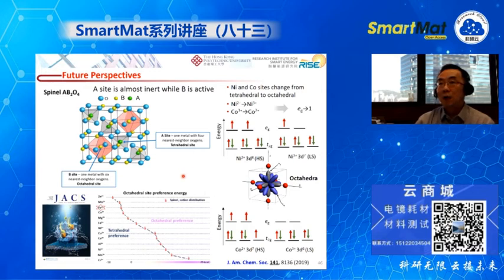And finally, we know that all the perovskite kind of materials have a basic unit of the oxygen octahedral. And this is an example for the spinel. Spinel also has oxygen octahedral, and the oxygen octahedral is considered to be the active center for hydrogen evolution and oxygen evolution. And we have done some work on the spinel structure, and we found that by tuning the eg electrons of the oxygen octahedral, we can control the oxygen evolution reaction activity.